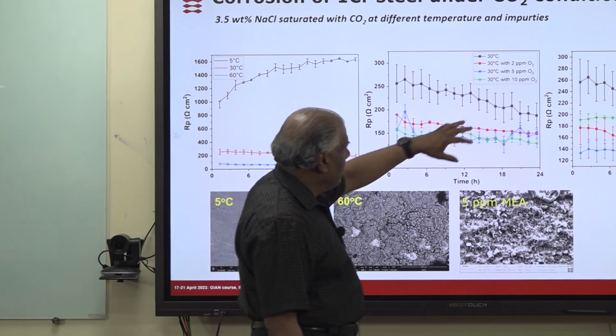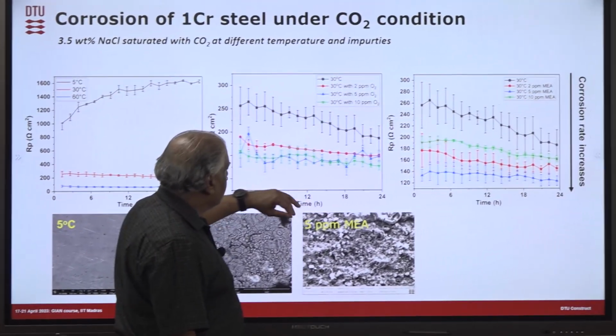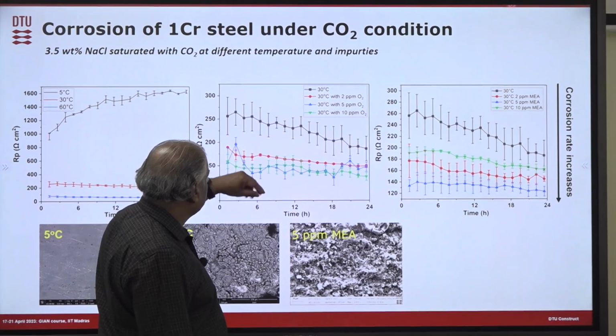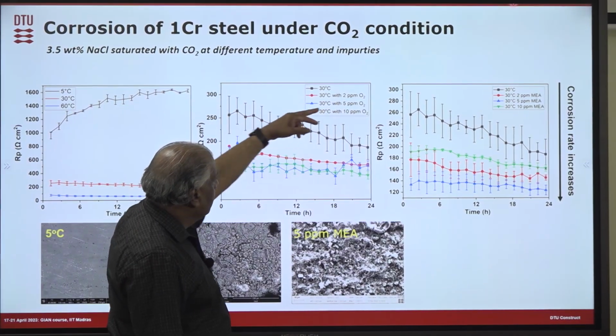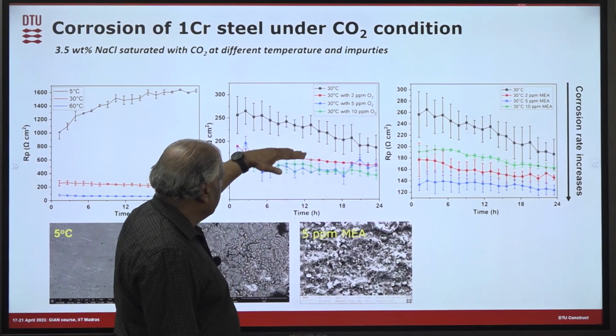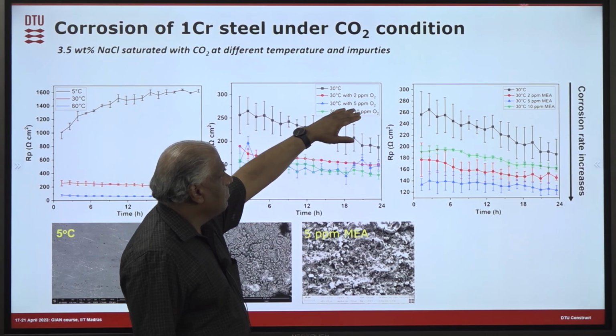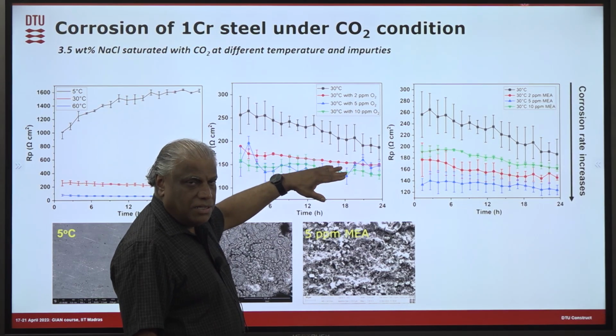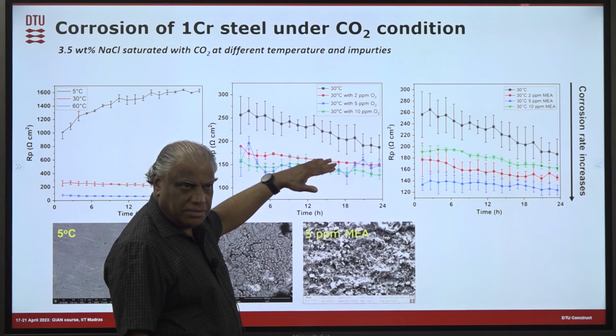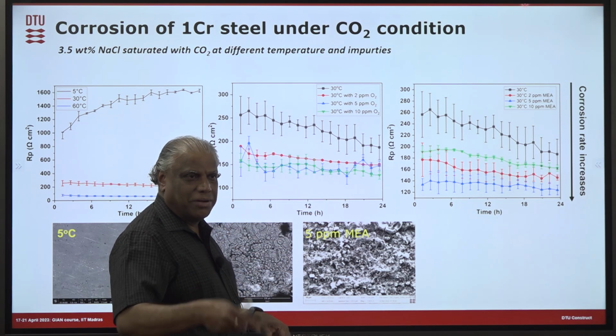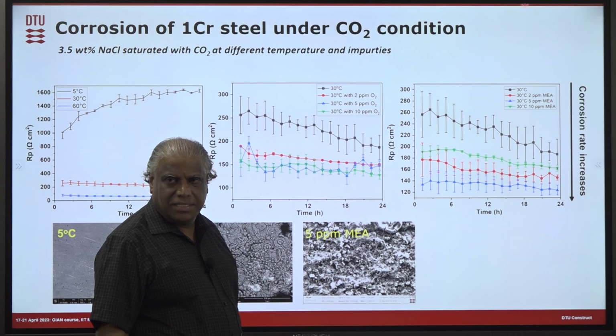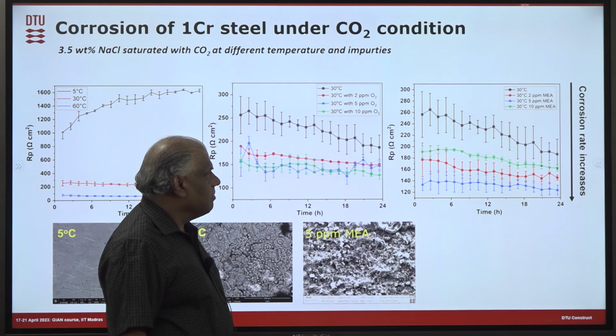This one we try to study the oxygen concentration effects. So you can see that when you add 2 ppm oxygen, there is an increase in the corrosion rate, but even if you add more oxygen concentration, it is not changing that much, because there's also a saturation value, right? For oxygen, the amount of oxygen that we can have in the water.